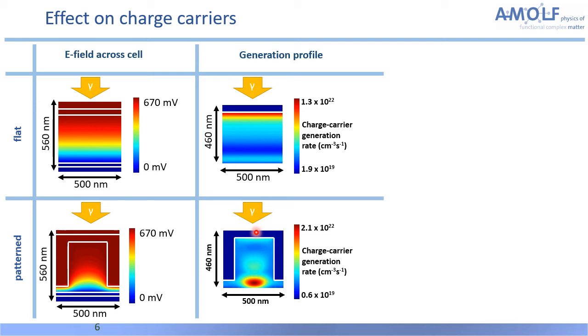But due to the fact that mobilities in zinc oxide are much better than in the quantum dot solid, just getting here would already be really good for extraction. And that's basically where the electric fields come into play, because if you look at the direction, then you can see that the electric fields will basically aid the electron in getting to the interface so that it can be extracted much sooner than you would have in the planar case, for example.